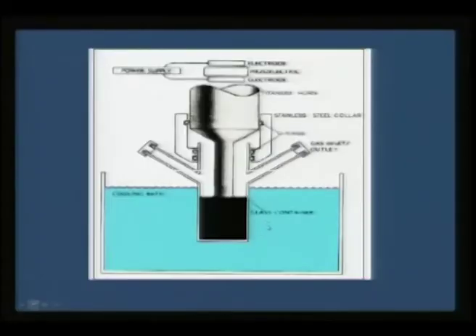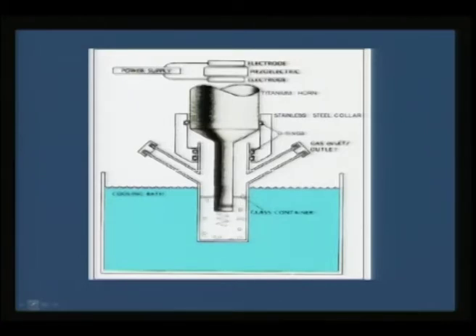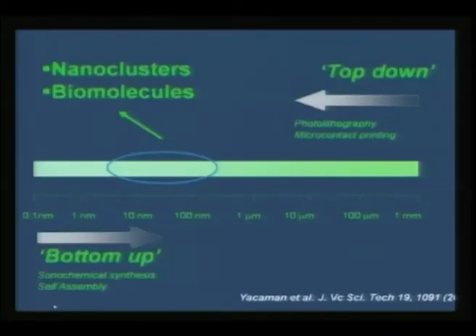One caution that we need to take during sonochemistry is you need to apply an ice bath, so that the hot spots which will ultimately keep heating this vessel will be kept at low temperatures, otherwise your organic solvent can evaporate. So for most of the reactions we can use decalin as a solvent, which is preferably used. So this is a cartoon which tells typically how a sonochemical synthesis works. Now when we talk about sonochemistry for material synthesis, it is two ways.